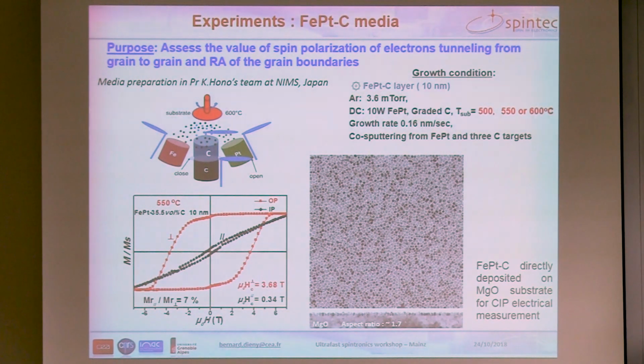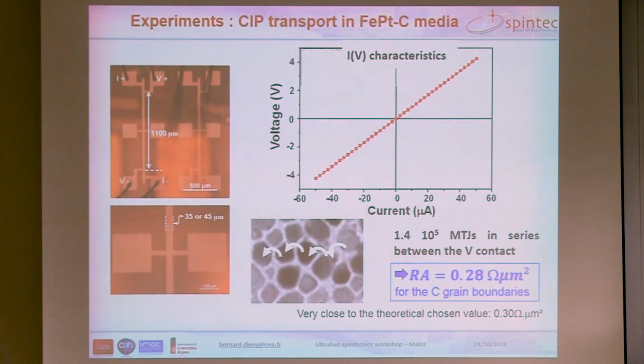And so this is what the hysteresis loop looks like here with coercive field of the order of 4 Tesla. And this is the structure of the media. And here, since afterwards I am going to explain that we want to measure the transport property of this film when the current is flowing in plane, in order to measure the tunnel magnetoresistance through these grain boundaries. So we deposited this material directly on the magnesium oxide substrate to avoid shunting in any metallic underlayer.